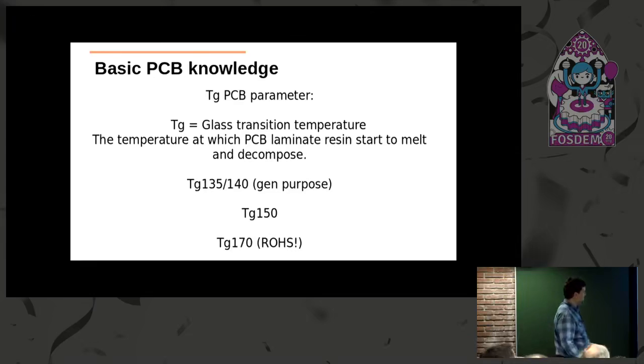Another parameter is the glass transition temperature. This is the temperature at which the epoxy resin in the PCB starts to melt and decompose. If you order your PCB at a PCB manufacturer, you will have options for the TG, starting from 140 and ending at 170. If you have RoHS devices, you should go to TG 170.